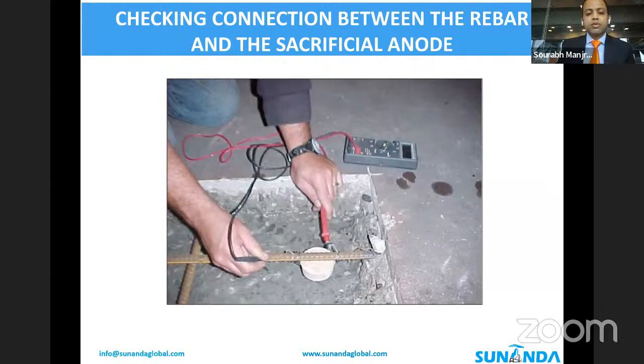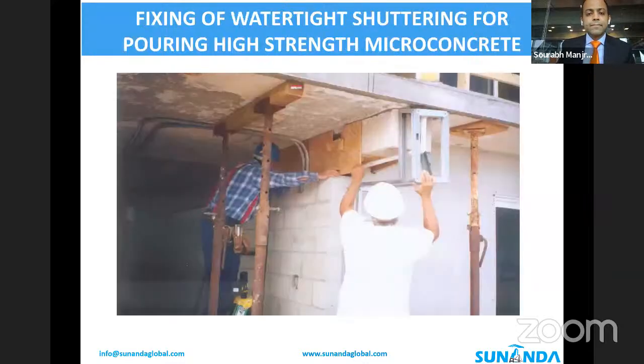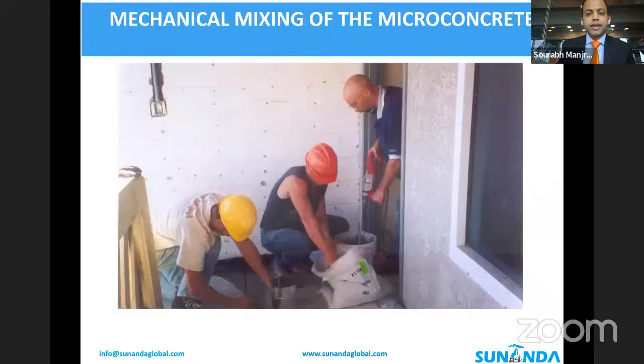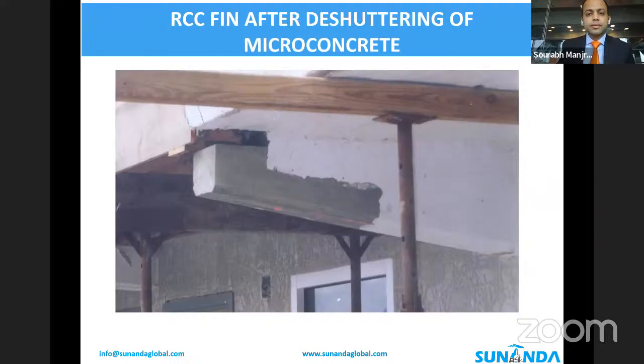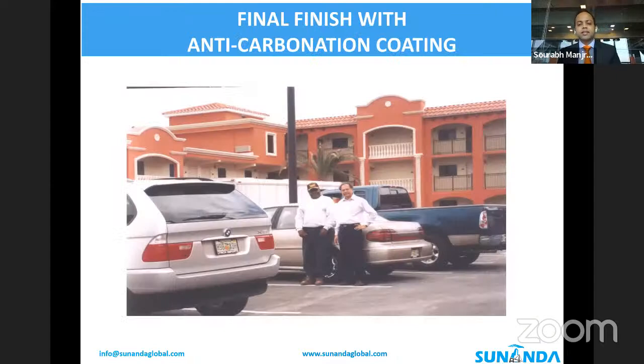This is back now to Hotel Cabana at Daytona Beach, Florida, where anodes were installed and checked at every place for connectivity with the steel. Shuttering being put in place for pouring of high strength micro concrete. Mechanical mixing of the micro concrete. And this is what it looked like after deshuttering. And finally, the chemically resistant anti-carbonation coating for the entire structure.